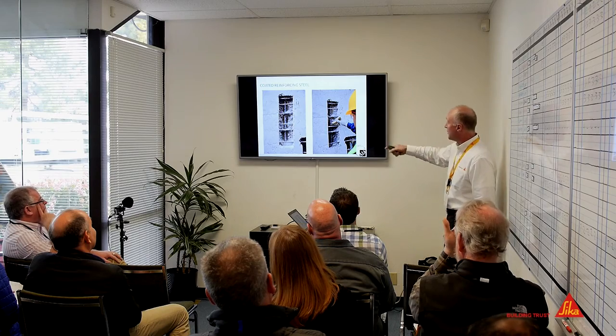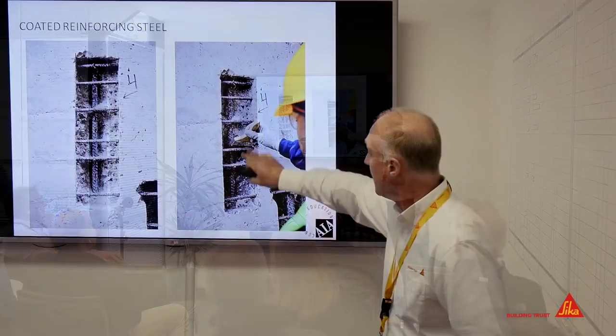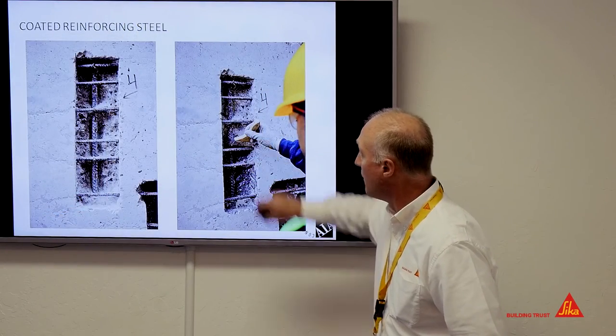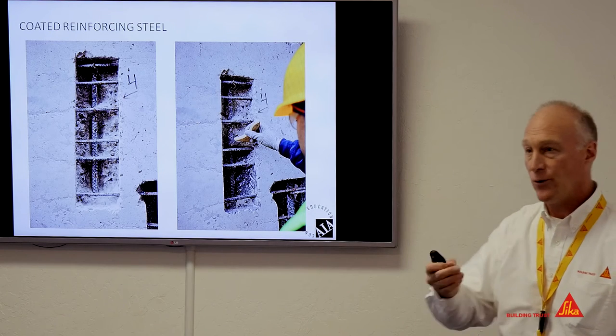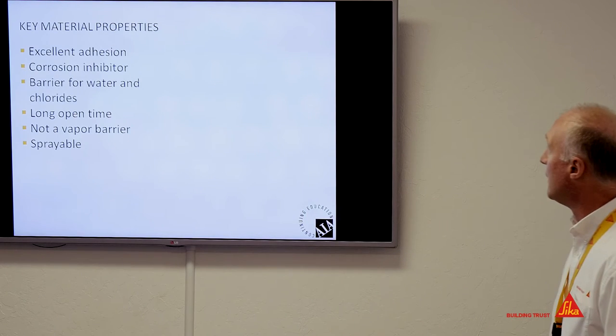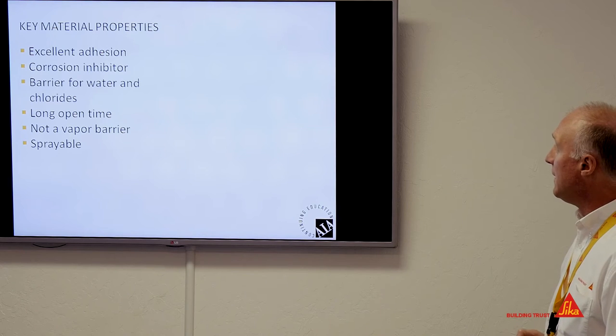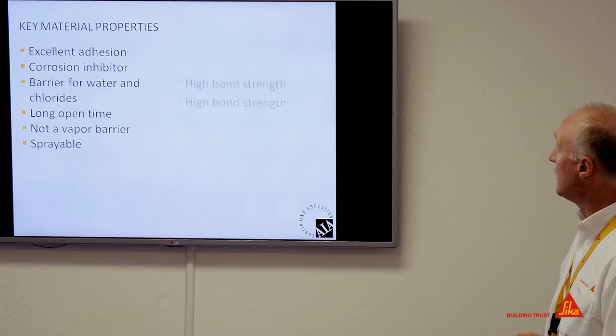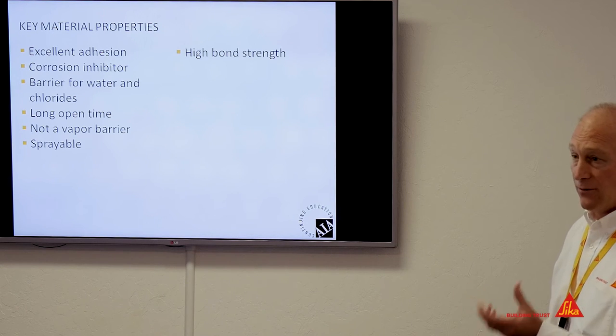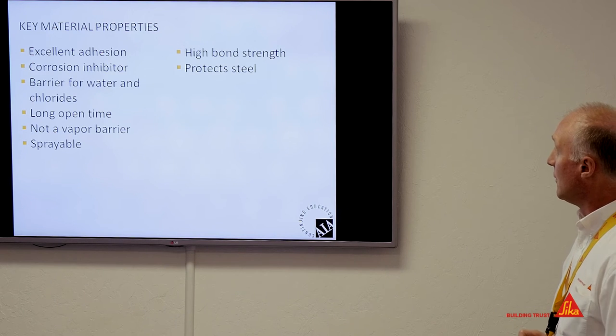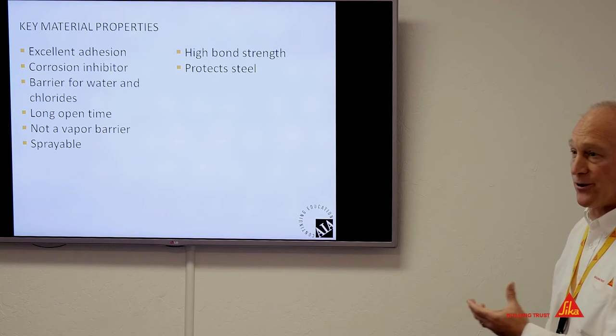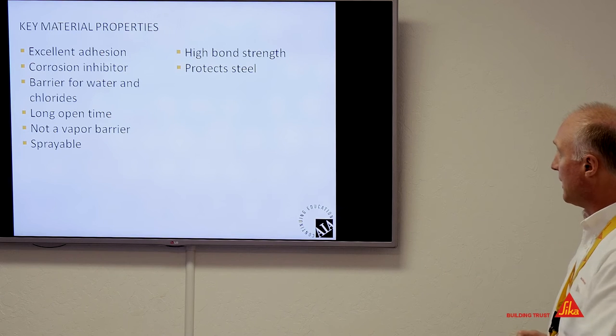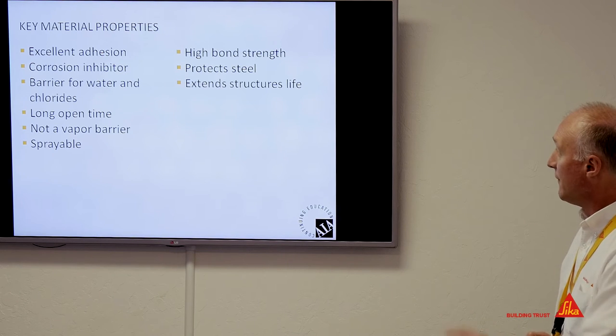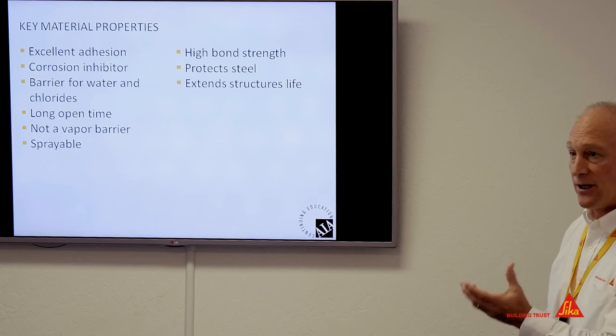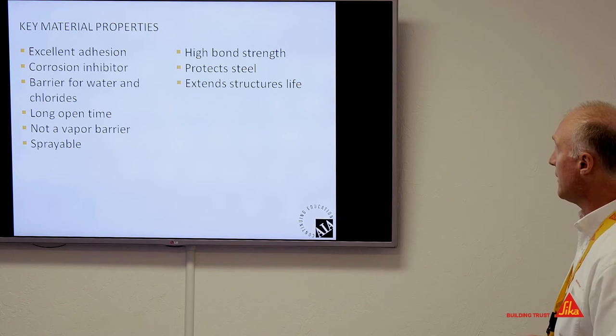So the excavation has occurred. They're priming the steel. They're also applying a bonding agent to the substrate. We'll do that this afternoon. The key properties here would be excellent adhesion, because that's going to encourage high bond strengths. A corrosion inhibitor in these materials is a good idea, because that'll help protect the steel. If it's a barrier to water and chlorides, that's going to extend the life of the structure.